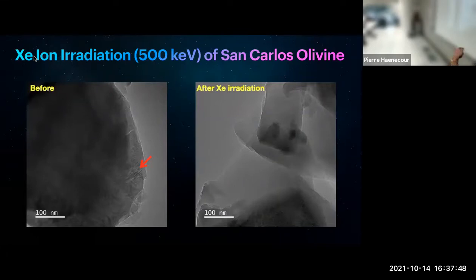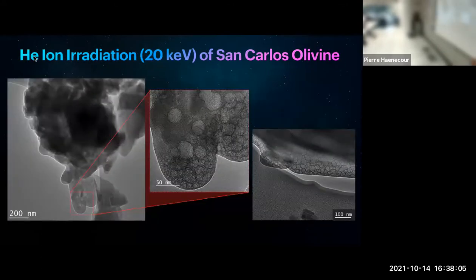And then you see, just after the xenon irradiation, so the high temperature irradiation, you basically lost all the crystallinity in the sample, and so it was completely amorphized. So we went from crystalline San Carlos olivine to amorphous silicate. In terms of the helium irradiation, what we see is that we actually implanted helium ions into the sample. You can see here the small bubbles inside the sample, all around the edge. So it's actually trapped inside the olivine grain. You can see it on the edge where it's thin enough to image. So it's full of those helium bubbles.